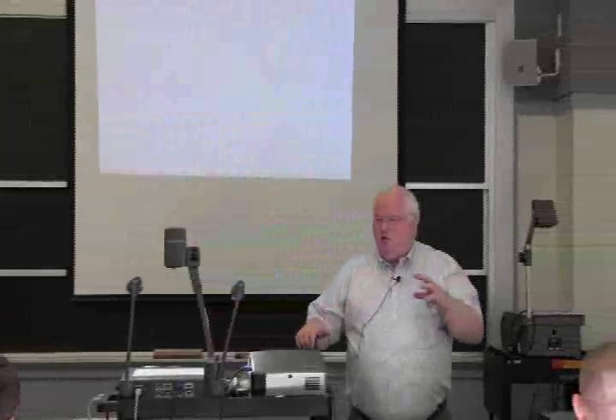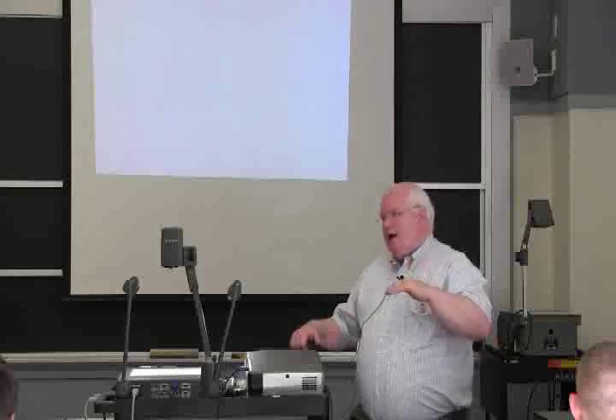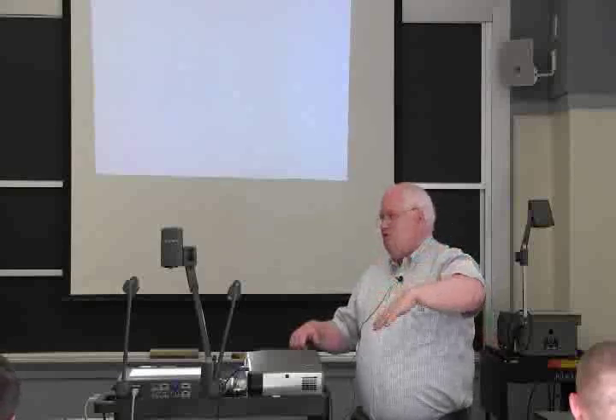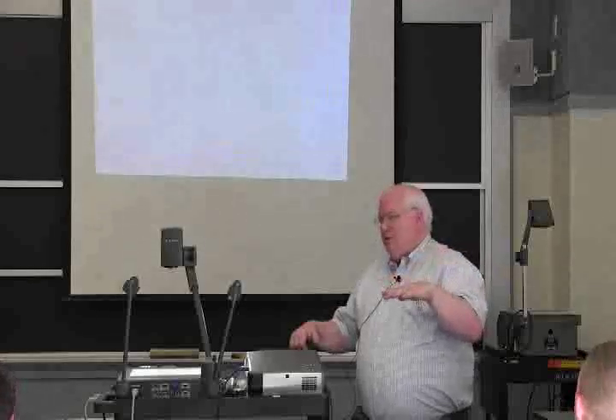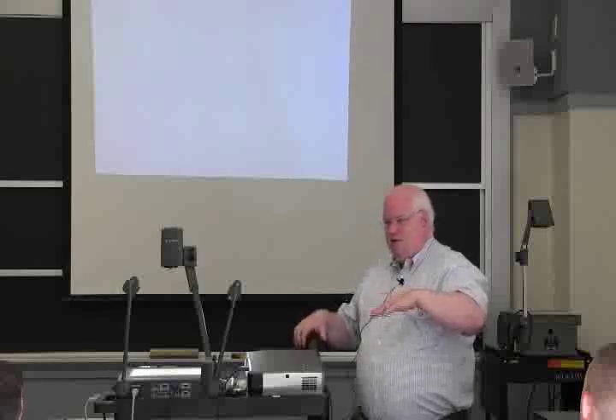Now, there's one other thing. Flemings actually invented a process in the late 60s. I talked about the cellular growth and stuff. In order to inhibit the dendrites from forming, you can grow in a gradient furnace, and the steeper the gradient you have, this is hundreds of degrees C per centimeter or so, you can keep the dendrites from forming. And you sort of end up with zone melting, but if things aren't too bad, you're not sweeping everything ahead if you design it properly.